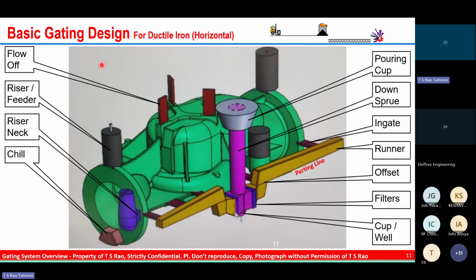So there are three purposes for the flow offs. The first purpose is when we pour the hot metal, the gases which are accumulated within the mold environment are released through the flow offs so that there is no gas entrapment within the mold environment. And second, the first metal when we pour is likely to carry the loose particles within the mold. The metal mixed with the loose sand particles will get out first, then the clean metal gets in. And the third purpose of the flow off is whenever it requires a little pushback, the flow off also can feed the casting as required. This is a very basic gating design for horizontal parting line sand casting.